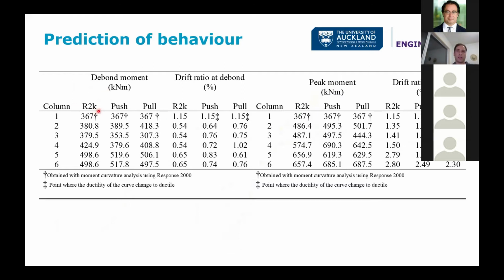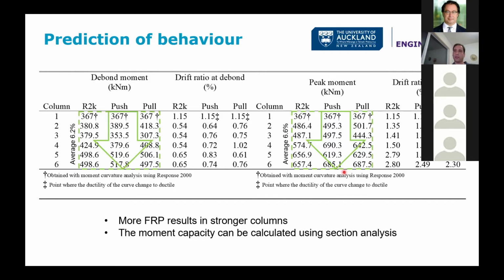R2K, by the way, is just using Response 2000, which uses moment curvature and section analysis. As we increased the amount of longitudinal FRP, the moment increased, both the debond moment and the peak moment. And I could calculate that quite well, I think. 6.2% difference, 6.6% difference. So I think it works. It's just section analysis, with one more material with different properties, but it can capture the moment capacity.